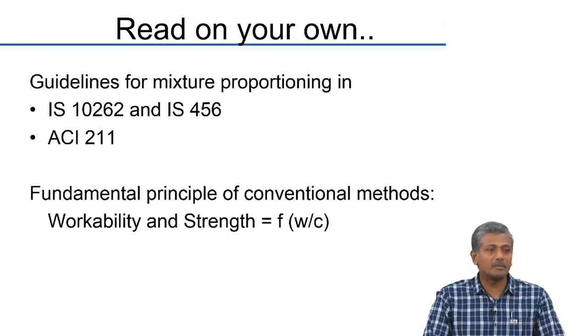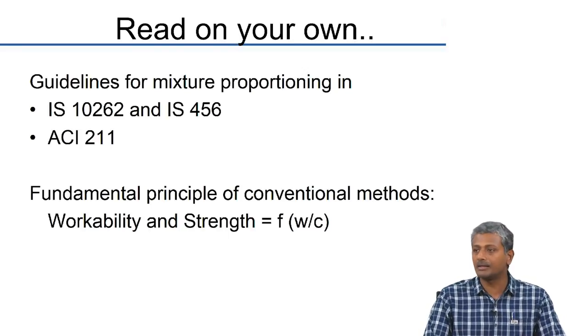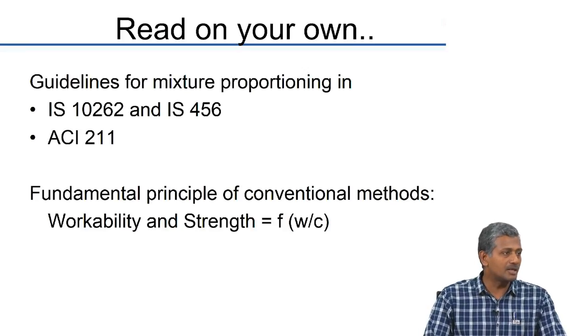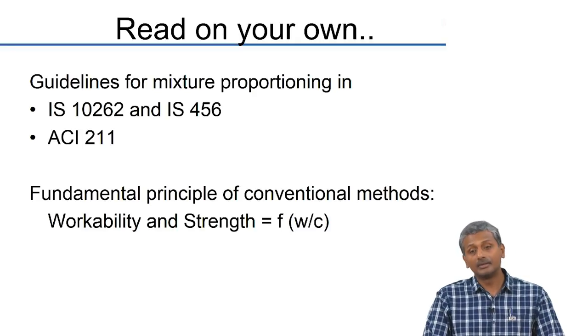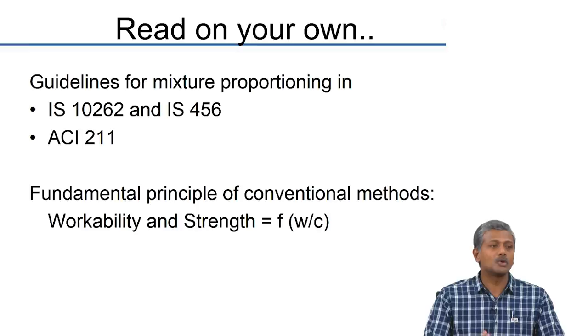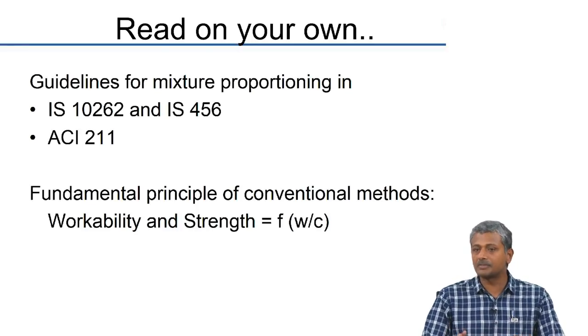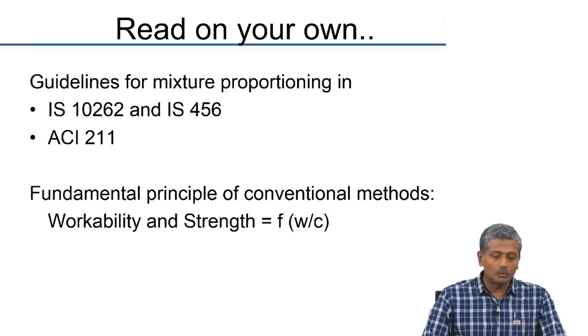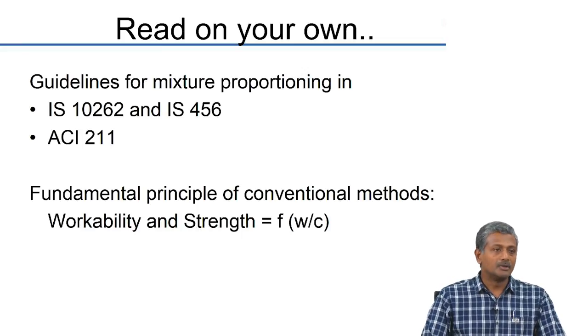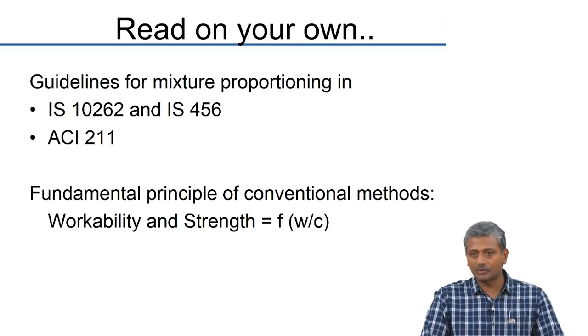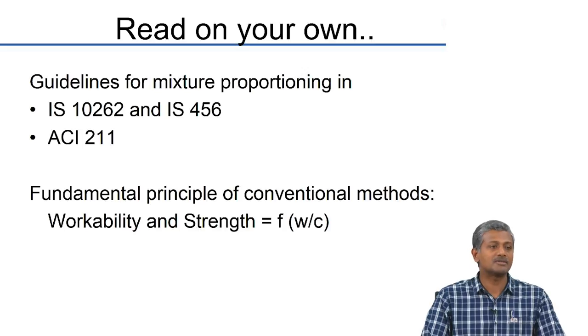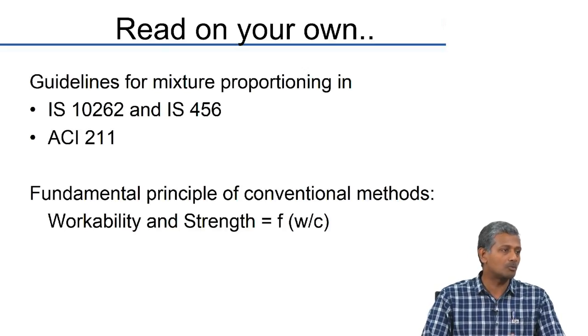ACI-211 is the American Concrete Institute guideline which is on a similar line as IS-10262. Of course every country has their own mix design guidelines — EN-206 is a European guideline, or rather European norms for concrete, and those also link you to different kinds of mix design guidelines. The fundamental principle of all conventional design methods is that your workability and strength are both a function of the water-to-cement ratio. In modern principles also, strength is primarily determined from the water-to-cement ratio.